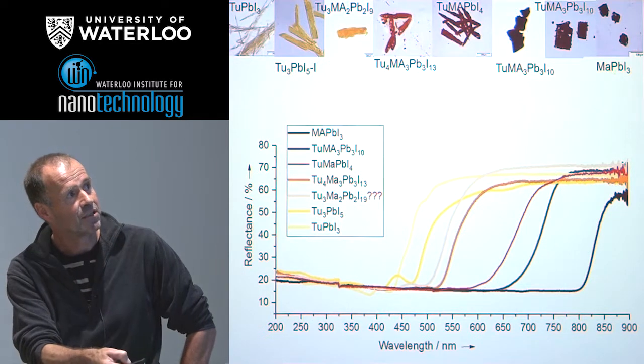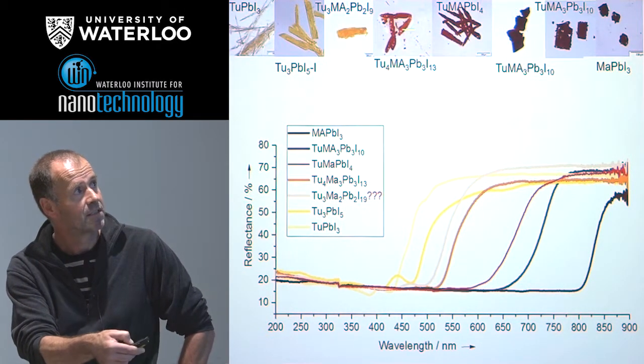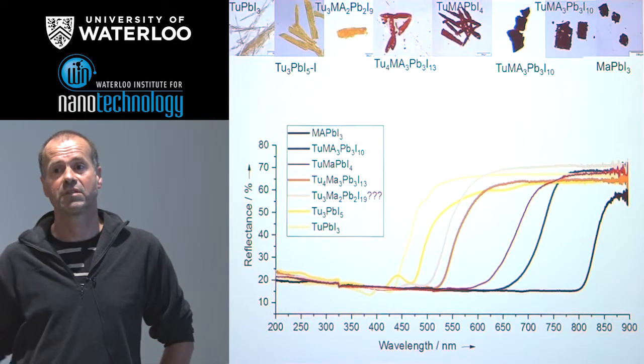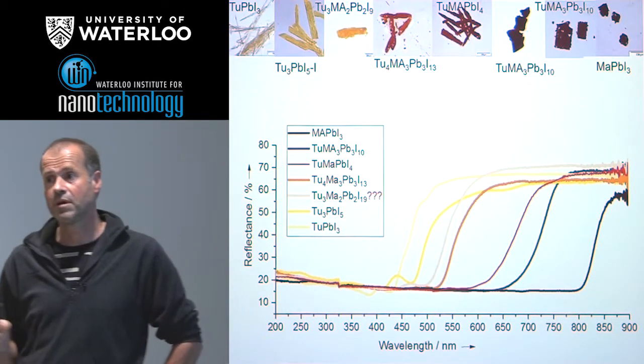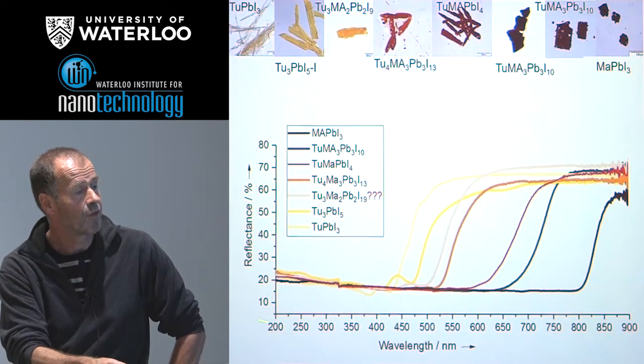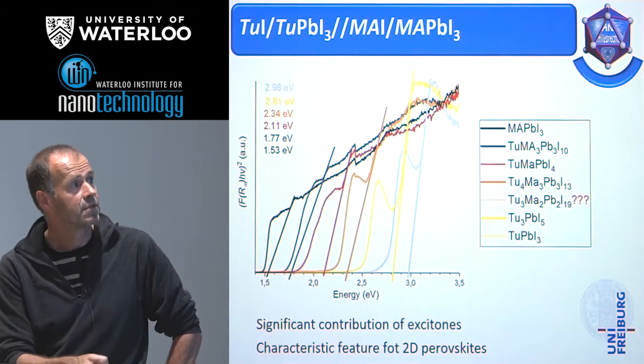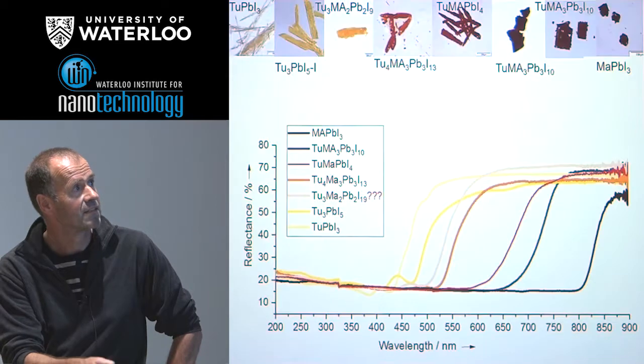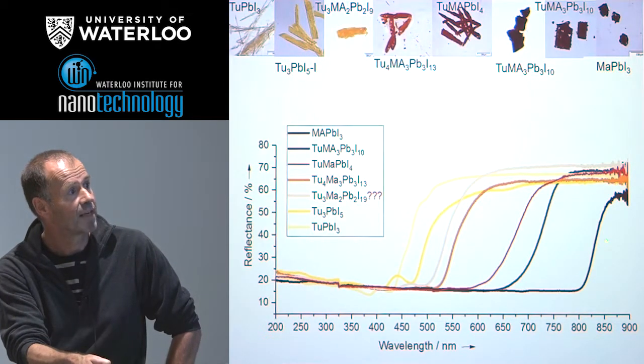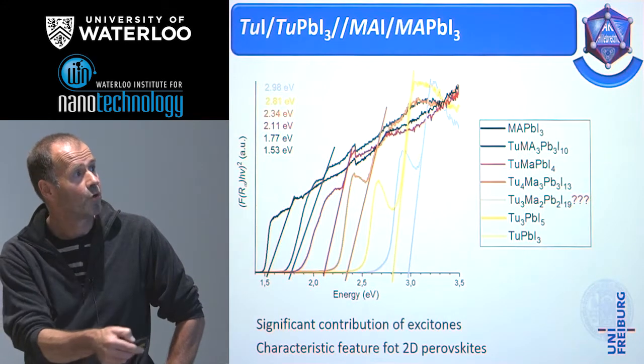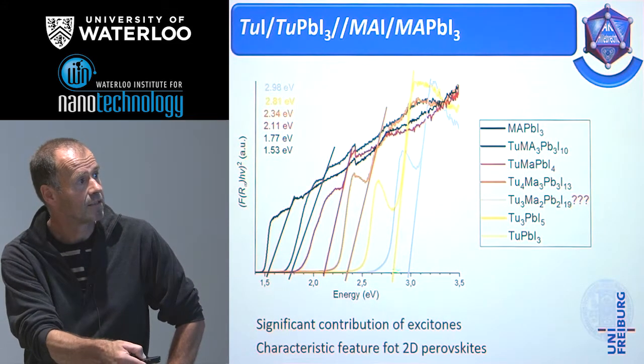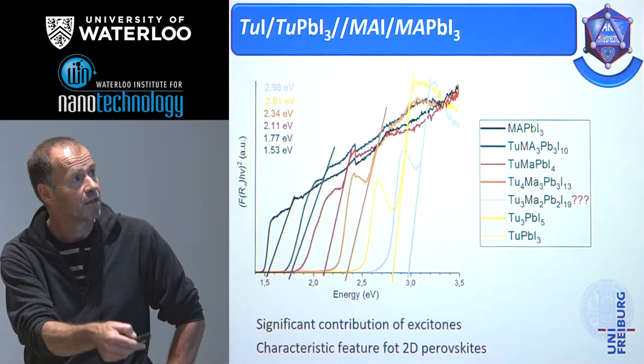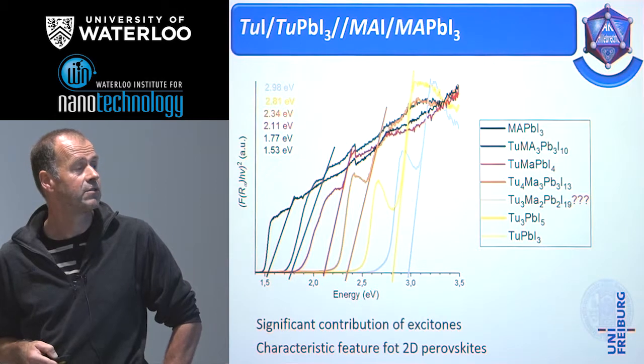The optical properties show clearly that the extent of connection correlates to the color. That means the more edge-sharing lead iodine octahedra we have, the smaller is the band gap and the closer is the color to the black color. We could do the measurements and we measure the optical band gap, and you see it's really perfect, it goes the whole series from black to nearly colorless.